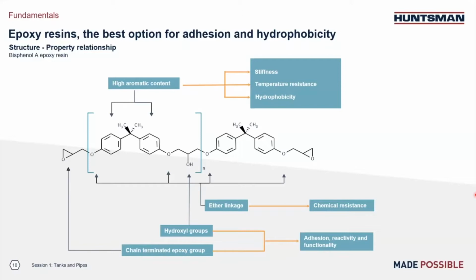So we all know epoxy resin-based coating has been used for many years for industrial protective applications because it has very good adhesion, excellent chemical resistance, and very good mechanical properties. So if we look at the epoxy structure, we can find out why. In this epoxy standard BPA type structure, we can see we have those aromatic rings, which give us the structure stiffness.